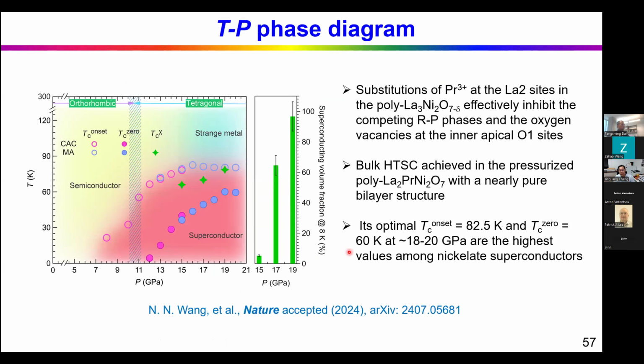So basically, this above result confirms that the praseodymium doped sample has a nearly pure bilayer structure with negligible oxygen vacancy at the O1 site. And in this sample, we achieved bulk high TC superconductivity with a transition temperature, especially TC0, around 60 Kelvin, which is so far the highest value among the nickelate superconductors.